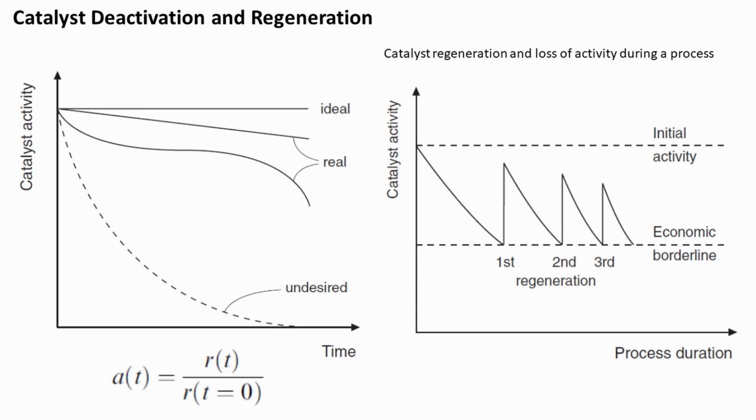Indeed, this condition can cause formation of large quantities of carbon filaments, which plug catalyst pores and void volume, pulverize the catalyst pellets, and bring about process shutdown all within a few hours. Not only does the decrease in catalytic activity lead to loss of productivity, it is also often accompanied by a lowering of the selectivity.